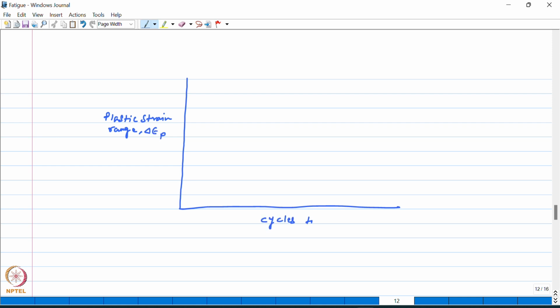And the usual way of presenting the low cycle fatigue data is in terms of plots between plastic strain range and cycles to failure. This is basically a straight line like this, which is given by this relationship, which is known as the Coffin-Manson relation.